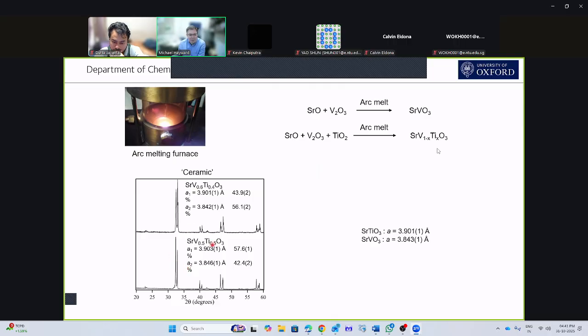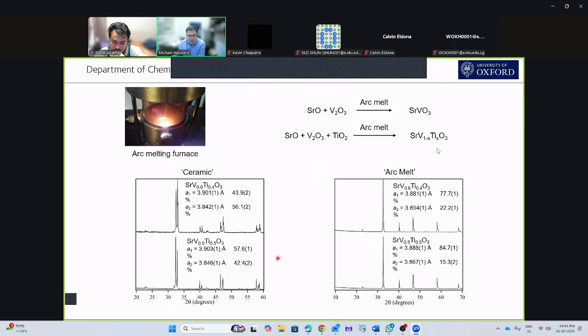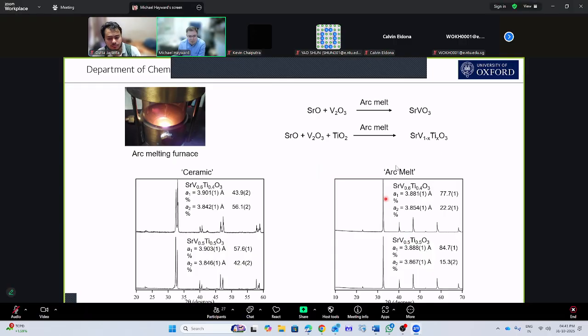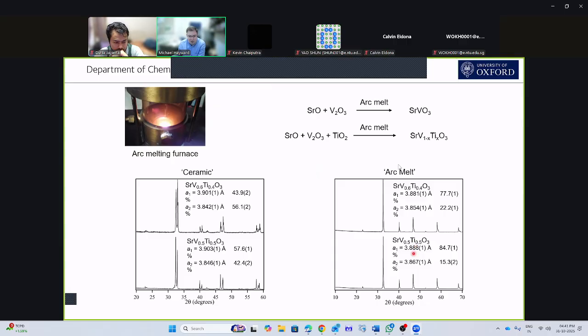If I take the same compositions and arc melt them, now you can see I get what looks like a single peak. Now it isn't quite. We do have two phases here, but you can see their lattice parameters are much more similar, and we have a significant majority phase, showing us that we are getting some titanium dissolved in the vanadium material. And so what we could do here is, you might think, well, I can make this a bit better by annealing, but if I anneal the material, it goes back to this two-phase example.